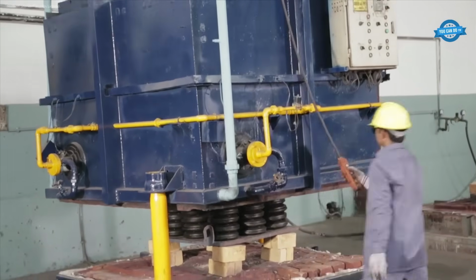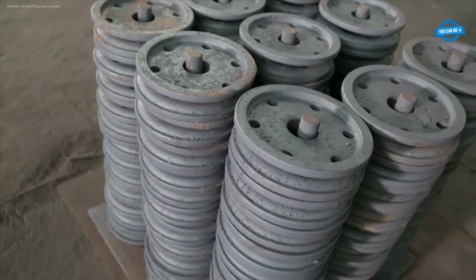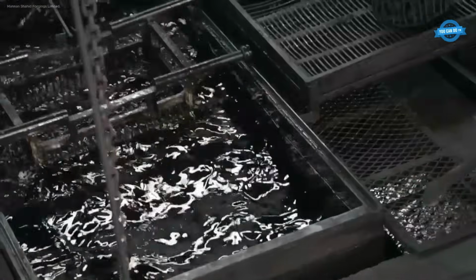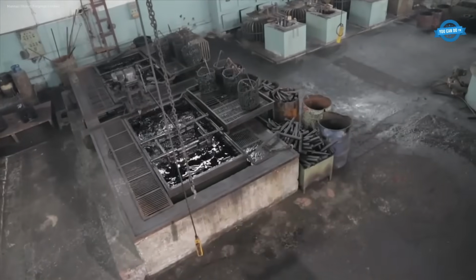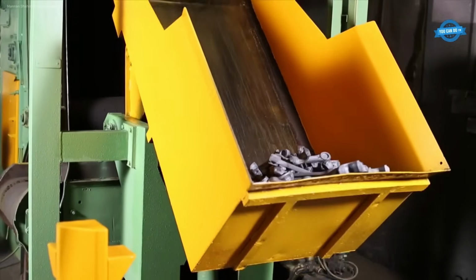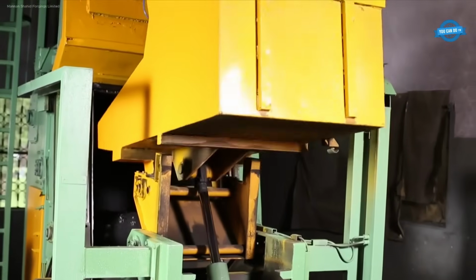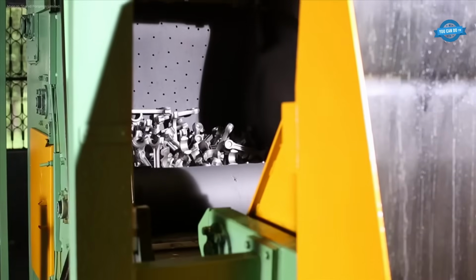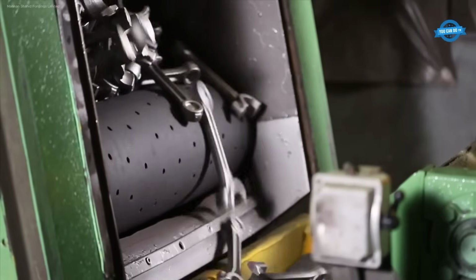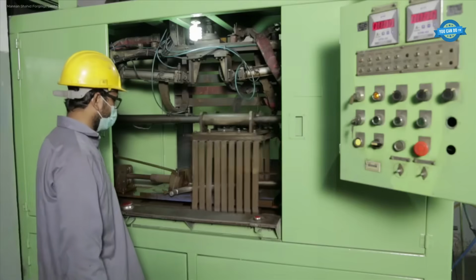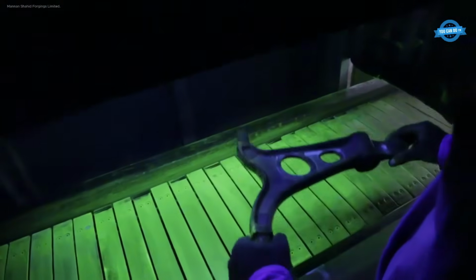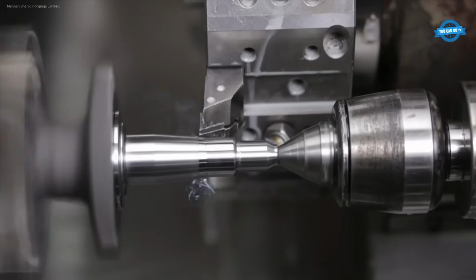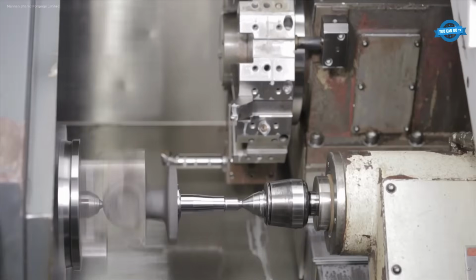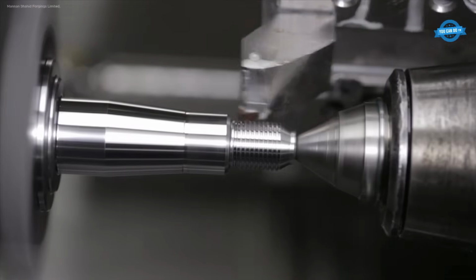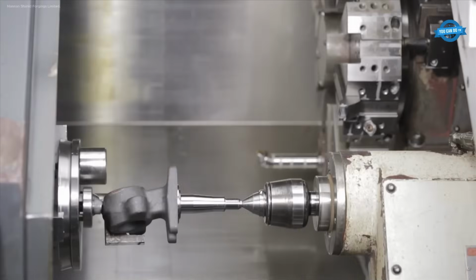Post-forging processes include normalization or isothermal annealing in gas-fired furnaces, followed by salt bath hardening to maintain temperature accuracy. Shot blasting removes scale, while magnetic particle inspection ensures all parts are crack-free. Components requiring further processing are sent to the machining plant, equipped with CNC turning, hobbing, milling, drilling, and grinding. Induction hardening of axles and spindles is also performed.